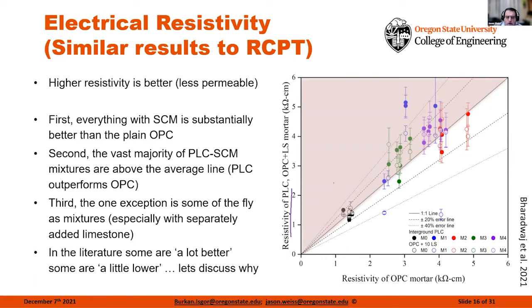The real takeaway here, and I want to just point this out, is that in general, everything that we've tested falls along this 1-to-1 line or slightly better. Now, why is that important? Because an OPC performs exactly the same as a PLC. However, in many cases, the PLC could actually be better.